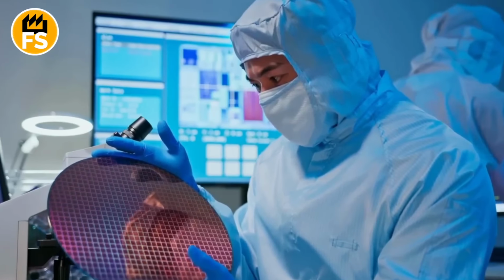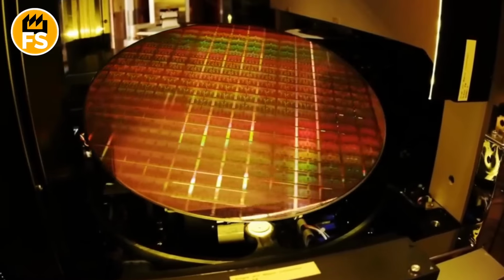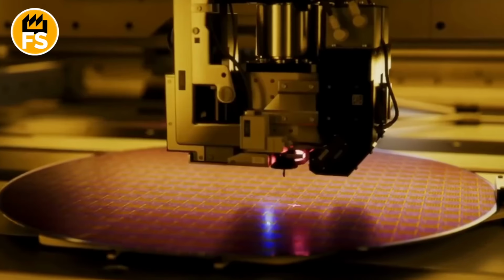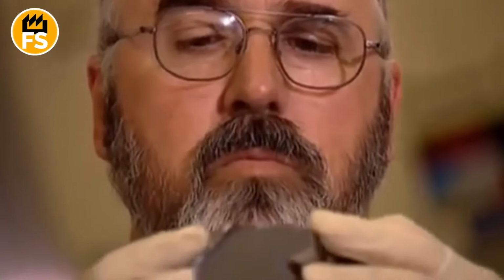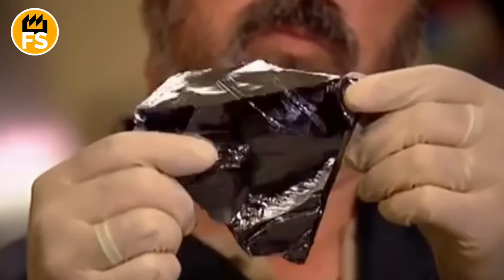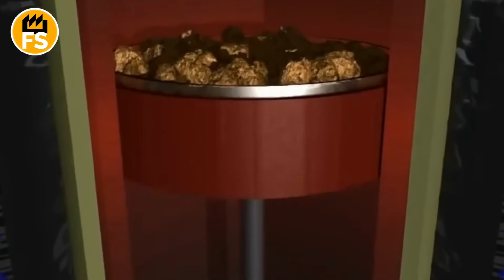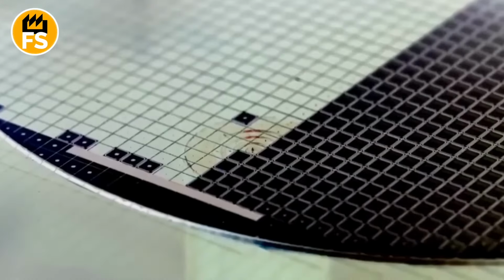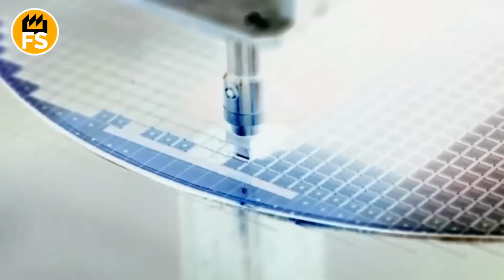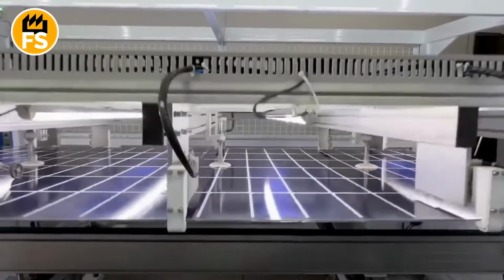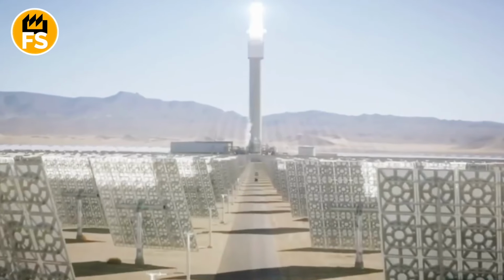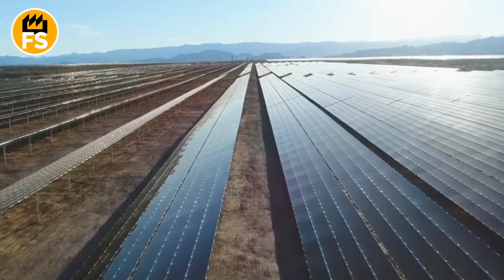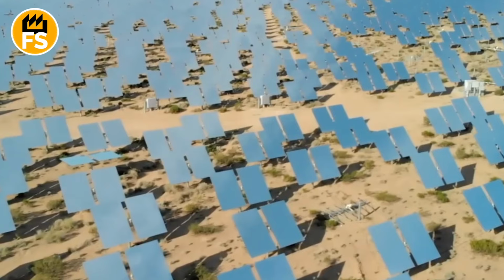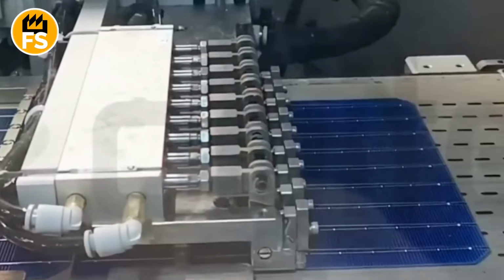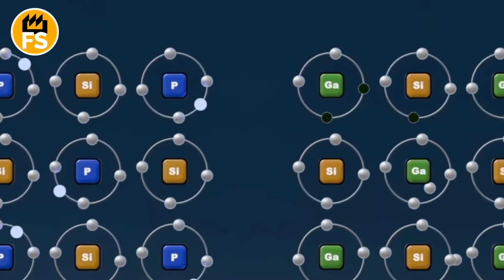Another key application is obtaining purer silicon suitable for electronics and photovoltaics. Metallurgical-grade silicon serves as the starting point for producing polysilicon, which gets purified to impurity levels in the parts per billion range. This ultra-pure material is what they use to form ingots and wafers for microchips and solar panels. Demand in this sector has shot up dramatically in the US over recent decades, driven by renewable energy expansion and the needs of data centers. To put the scale in perspective, manufacturing a single solar panel module that's about 11 square feet requires roughly 6 or 7 pounds of silicon in the form of high-purity polycrystalline material.